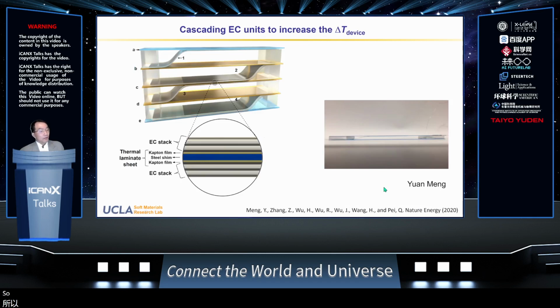While the maximum adiabatic temperature change can reach 12 degrees Celsius, that kind of operation condition is unstable. So for device fabrication, we have to lower the operating field to around 50 to 60 volts per micron. At this field, the temperature change achievable from the terpolymer is around 3 to 4 degrees C. That's not high enough for most cooling applications.